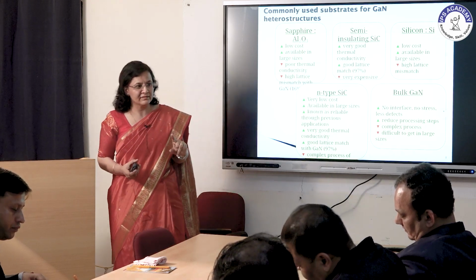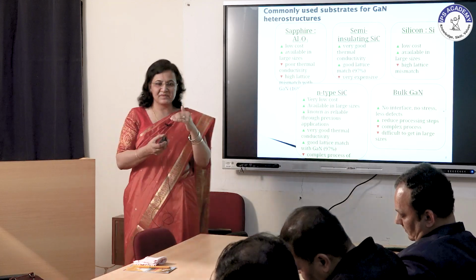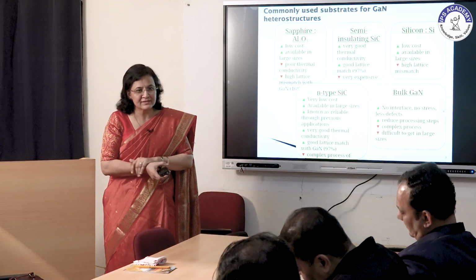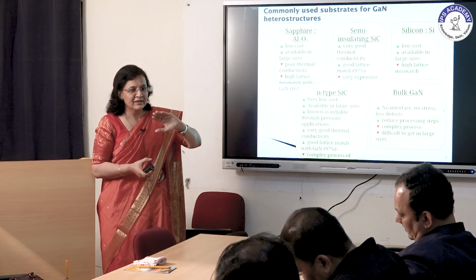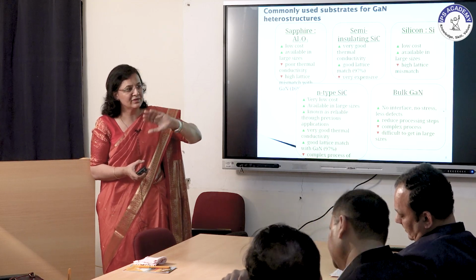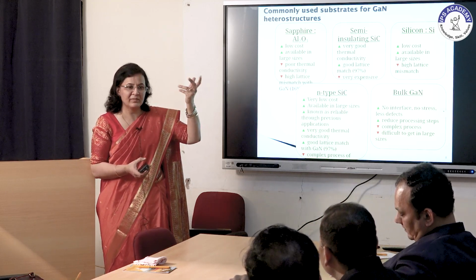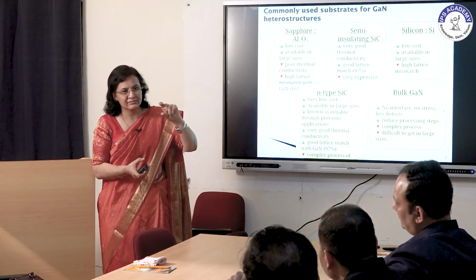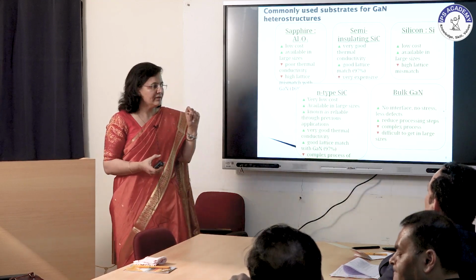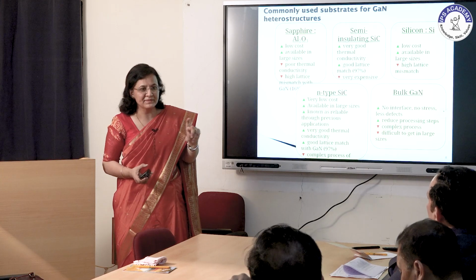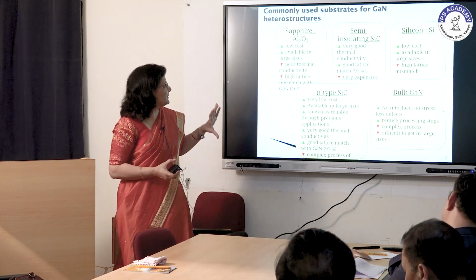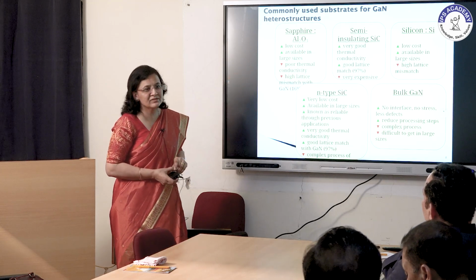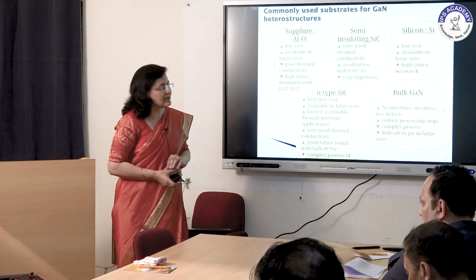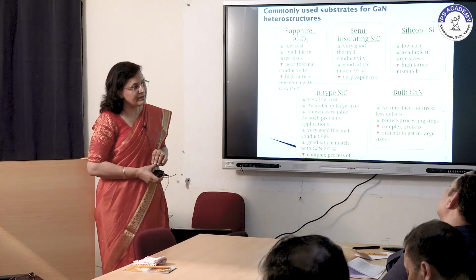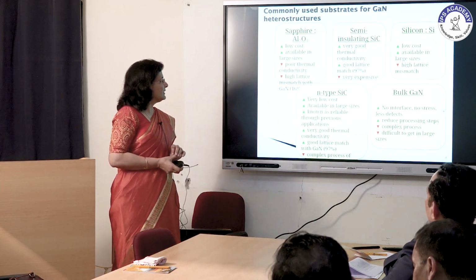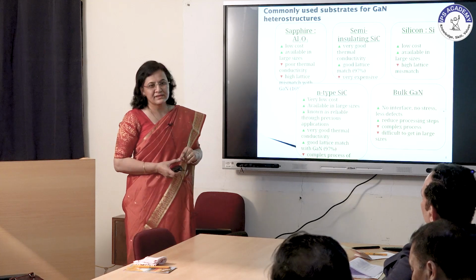Different substrates are used with the gallium nitride heterostructure. Substrates are the base on which your structure is formed. The same material is not necessarily needed for the structure, because making big crystal structures of the device material can be expensive or difficult. So you sometimes have a substrate of different material, and the upper structure is of different materials. The base commonly used for gallium nitride till now is sapphire: low cost, available in large sizes. The base has to be available in large sizes so your device is strong, but sapphire has poor thermal conductivity, so heat dissipation is bad.